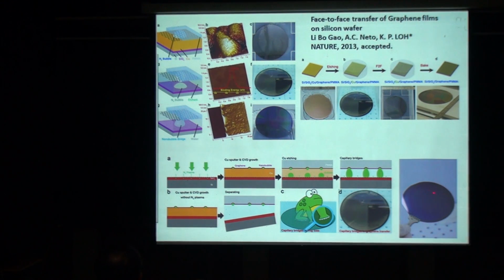The product, this graphene on silicon wafer, is a technological breakthrough, because currently everybody grows graphene on a copper foil. It's very difficult to grow on silicon, because silicon is lattice mismatched to graphene. But you can have copper on the silicon wafer, and you grow the graphene on the copper first. This is illustrated here by the diagram.